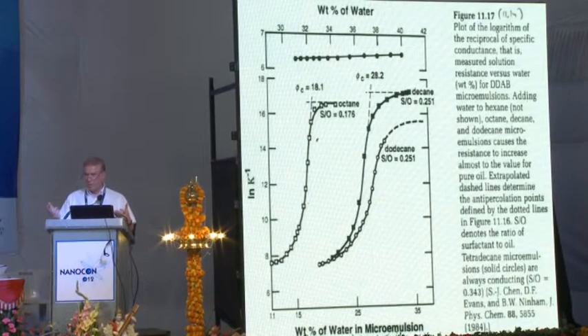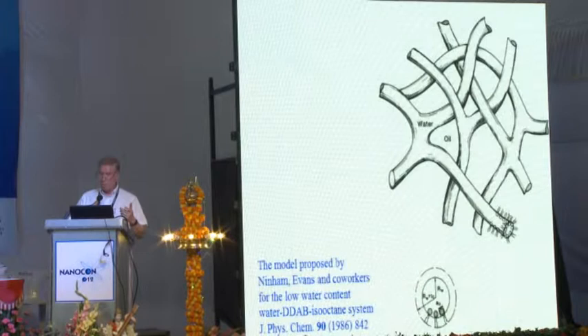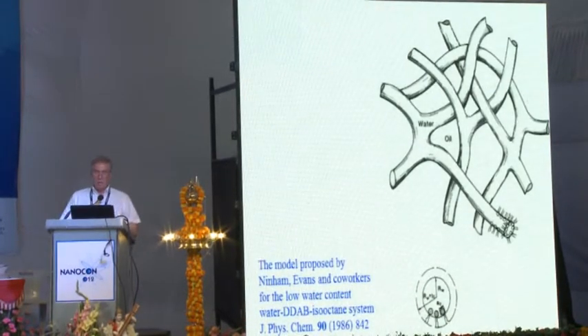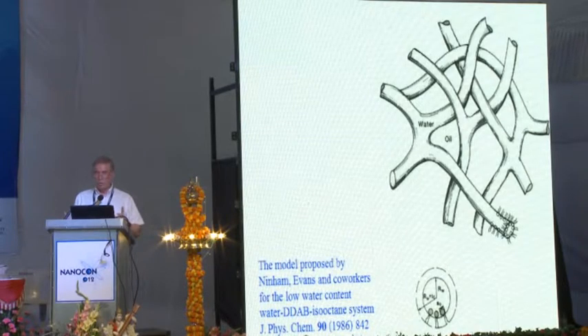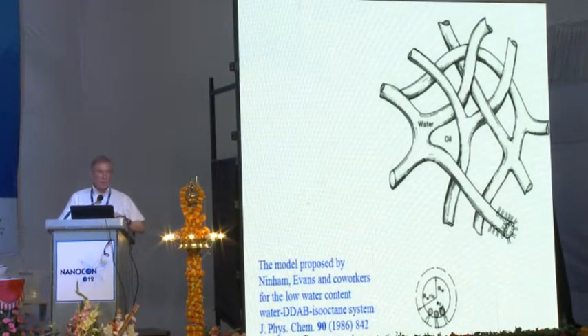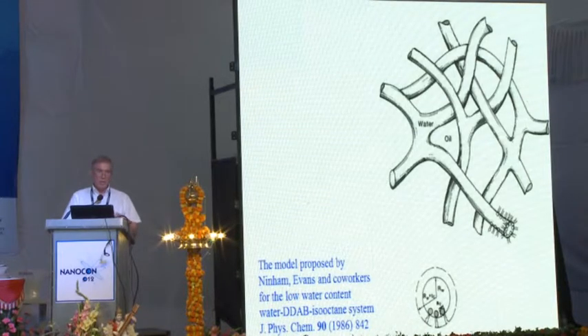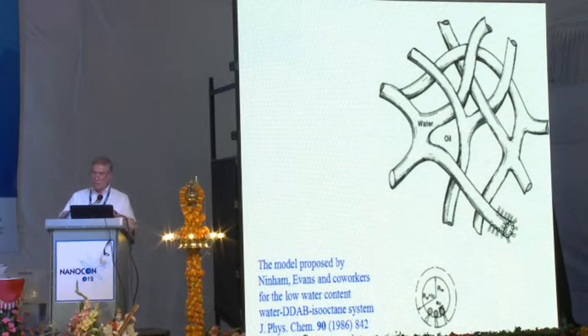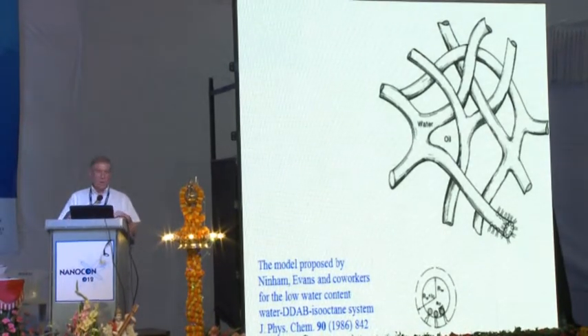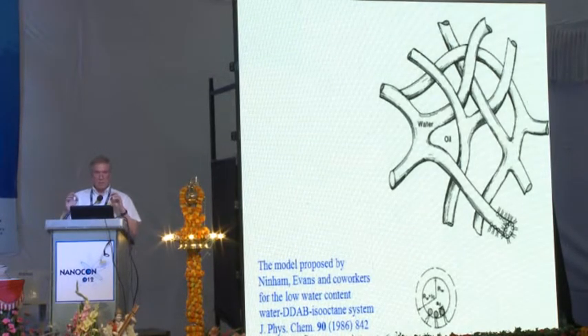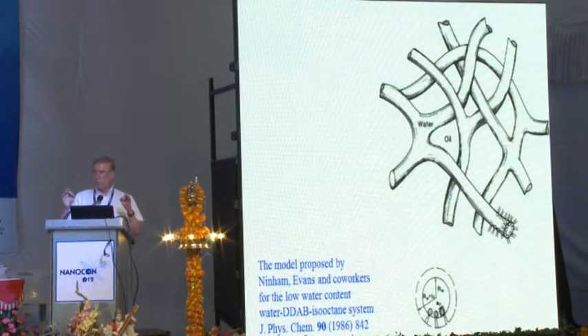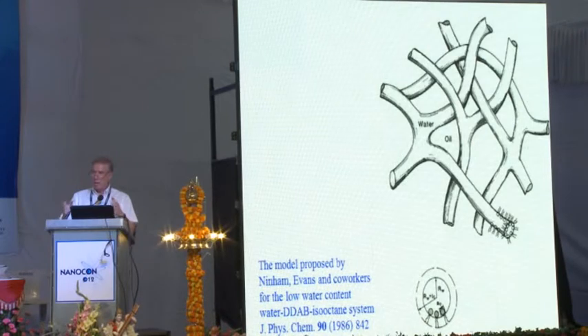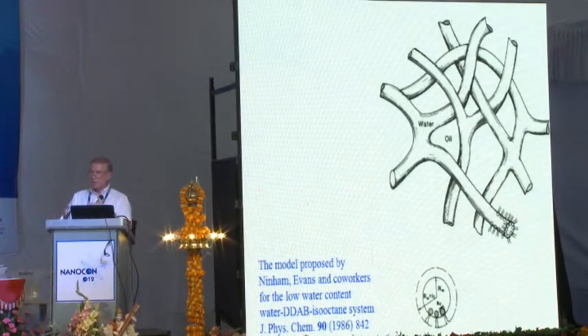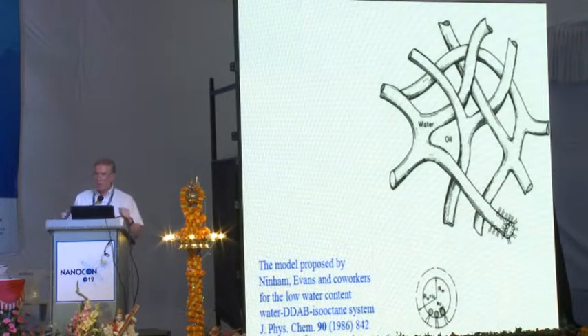This is counterintuitive, right? And they came up, since they're very good people, with a model which shows that at low water content, water forms a channel, a network of channels, of tubes, which span the entire system. And this is what gives it its conductivity. It's surrounded by oil. However, when you add some water, this structure breaks up, and what you get are individual, separate globules of water surrounded by oil. The water is not continuous. Only the oil is continuous, and that's why you get a high resistivity.